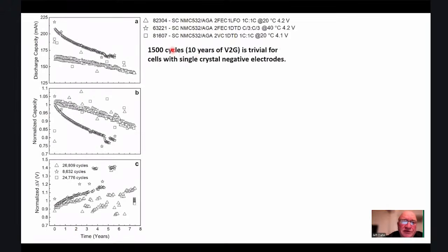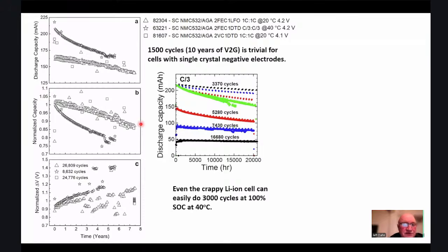So these are some other long test results that we've accumulated over the years. And what we have here in the triangles and the squares is cells tested for 7.5 years. The triangles and the squares are at 20 degrees C for cells charged to 4.1 or 4.2 volts. They've accumulated, where does it say this? Oh, yes, here down in this legend, accumulated 25,000 cycles and still just under 90%. The stars are a cell that's been testing at 40 degrees C for 6 years continuously, accumulated 9,000 cycles.